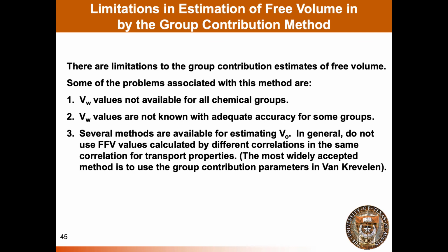There are limitations to this. There are not van der Waals volumes for everything. You go out and make some exotic structure that's never been made or considered before, there won't be a van der Waals increment or contribution for it. And there are some groups like the imide groups that are used in a lot of polyimides, for which there's some discrepancy in these van der Waals volumes, and so these things can cause this correlation to go awry. So it's not a physical law of nature, but it's a tool to use to correlate and rationalize data, and don't use it beyond that.